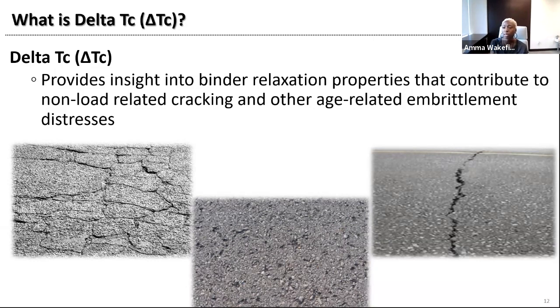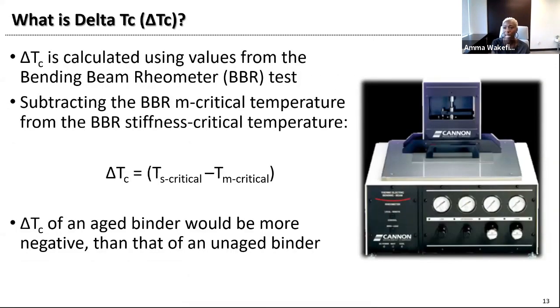It provides insight into the asphalt binder's ability to kind of relax after it's been under a lot of stress. And this is very important when you're looking at non-load related distresses. So things like block cracking or raveling, as you see in the bottom middle picture, or age-related embrittlement. So as the asphalt pavement gets more and more oxidized, its ability to relax these stresses becomes more and more difficult. And so delta TC gives you an idea of how well the binder you're using is able to relax those distresses.